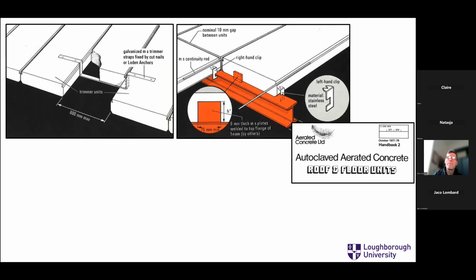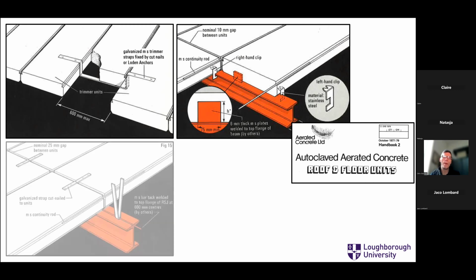So you'll see a steel I-beam there. I think maybe about 100 millimeter flange. So when you've got 100 millimeters, if you build it perfectly, you've got 50 millimeters bearing that side and another 50 millimeters there. If you build it perfectly, and I used to be a contractor, I don't think I built anything perfectly to the millimeter. I was within 5 or 10 mil most of the time. But if you were 10 millimeters out, suddenly instead of 50 millimeters, you're on 40 millimeters. And then you've got the cover to the steel, maybe another 10 millimeters. So then you've got maybe 10, 20 millimeters where the reinforcement is going over your bearing, if everything else is done properly and well. So this is where the issue is, and I'll come back to this.